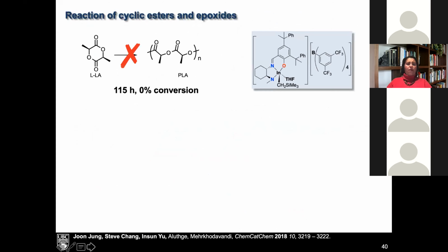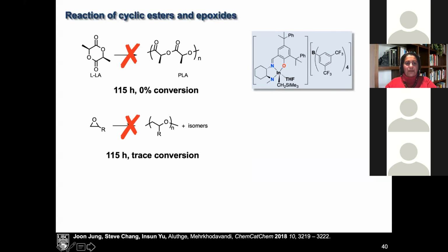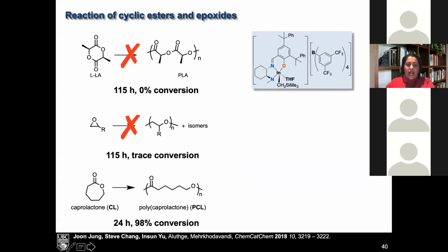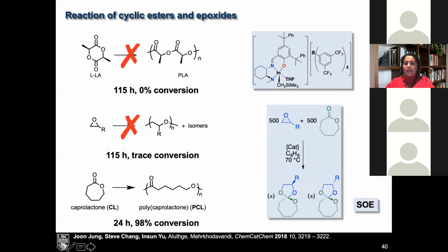And so they were completely unreactive towards lactide, which is kind of sad, unreactive towards epoxide under these conditions, somewhat reactive towards caprolactone, but very slow in terms of polymerization. But what they did was, when given an epoxide and a lactone, a 1-to-1 ratio of these monomers, under particular reaction conditions, what we were able to form is 100% conversion to spiro orthoesters. And they're a mixture of both enantiomers and diastereomers, but it's 100% conversion.